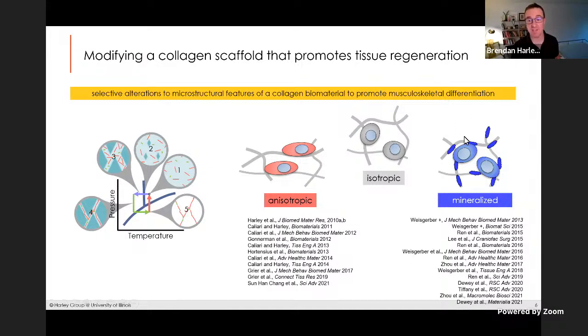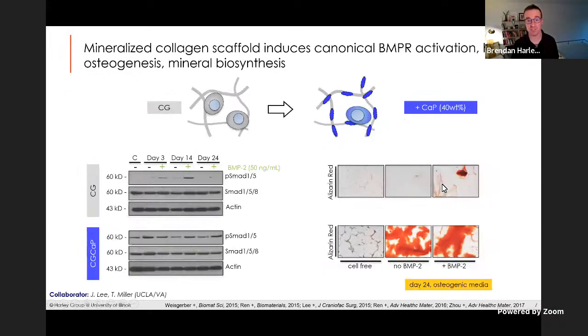And we have a variant that we've been very successful with over the last few years. So this material is about 40% weight mineral. It's got a calcium phosphate mineral like we have in our bones. We've tried higher and lower amounts of calcium phosphate. This is sort of inspired by development where our bones start out not being quite as mineralized as they are in adulthood. This seems to work really well from a healing standpoint.